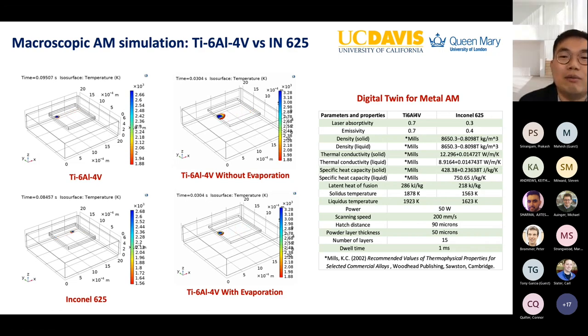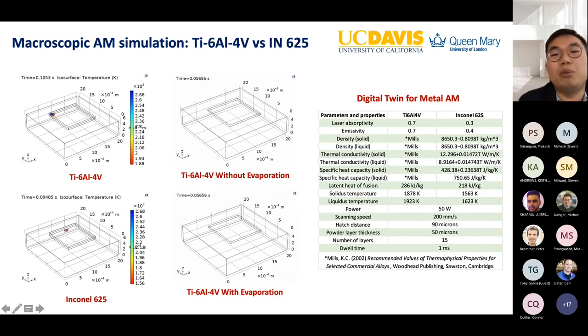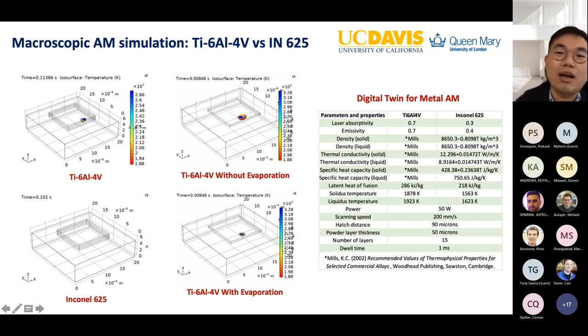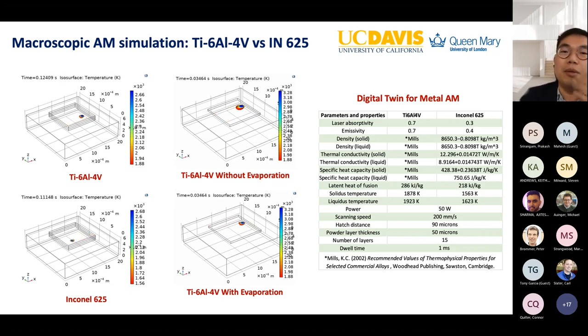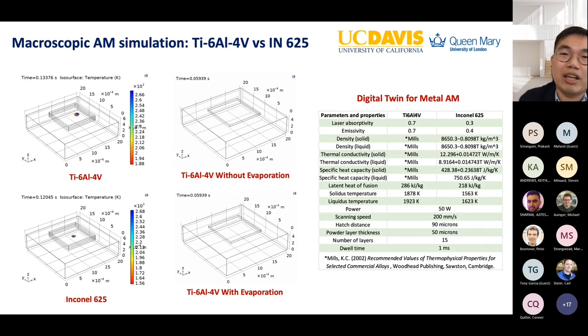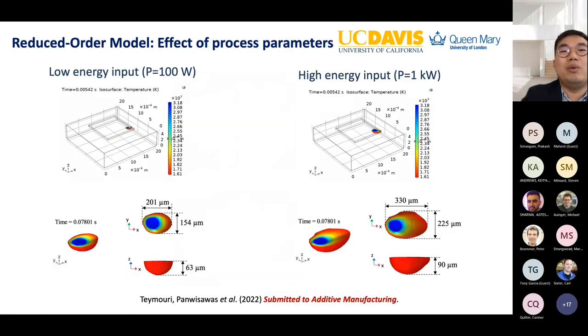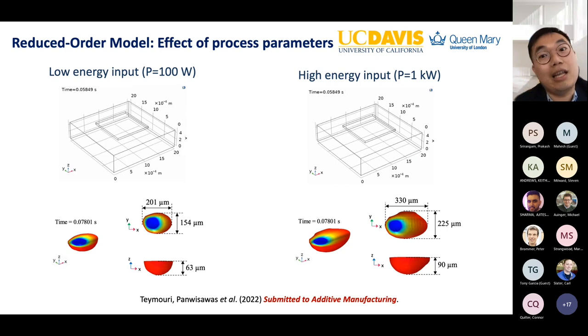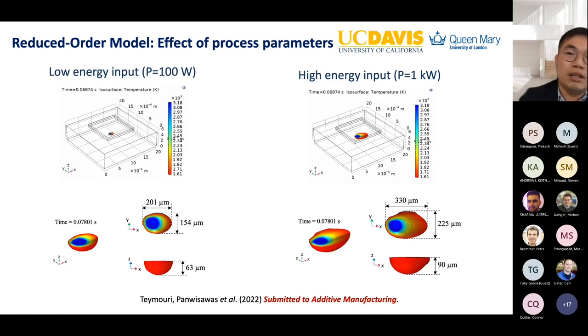Here is an example, like Ti-64 with and without evaporation. You will see that the predicted melt pool is rather different. And once you are building up in height, you won't be able to get a steady state melt pool, by the way. This is why we want to develop this kind of model. It's still not very cheap computationally, but it's cheaper than the high fidelity model, and can give some kind of predictive capability for further upscaling or a digital twin type of model. So this can capture some physics of prediction that you may anticipate from experiment.